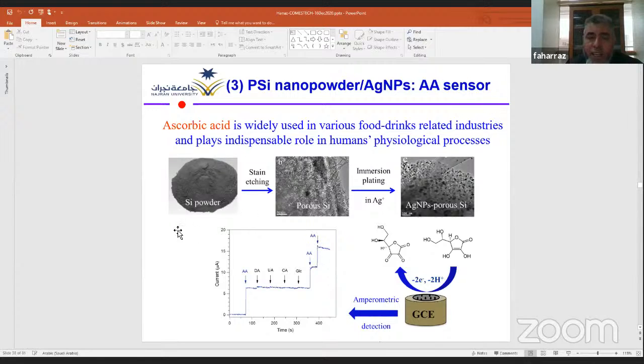We start our fabrication using silicon microparticles, powder, make a stain etching process, and obtain porous silicon nanopowder. Then we make some kind of immersion plating to deposit silver nanoparticles into the porous silicon nanopowder, and finally we obtain silver nanoparticles decorated porous silicon nanopowder.